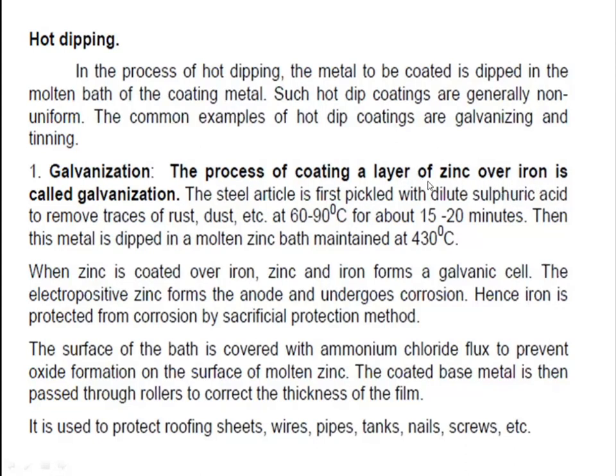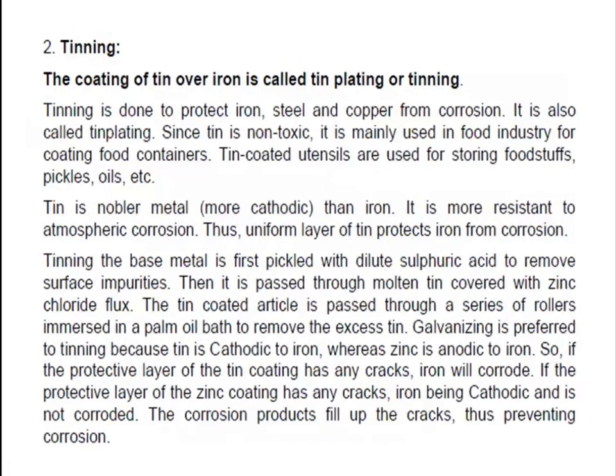Iron is covered with zinc metal and passed into the dilute H2SO4 solution at 60 to 90 degrees centigrade for about 15 to 20 minutes. Then this metal is dipped in a molten zinc bath maintained at 430 degrees centigrade. Zinc is coated over iron, and zinc and iron form a galvanic cell. The electropositive zinc forms the anode and undergoes corrosion, and the iron is protected. This method is used to protect roofing sheets, wires, pipes, tanks, nails, screws, etc. This is about galvanizing.